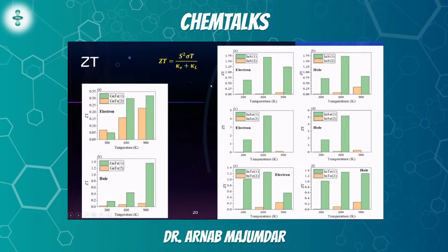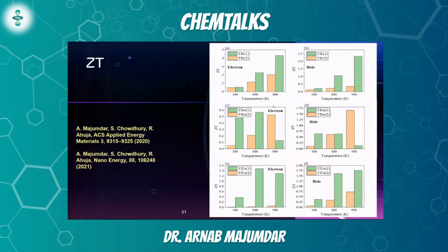But the interesting thing is that for all these systems, we can see that the ZT value for our systems, which is represented in green, is consistently higher and significantly higher compared to that of the AX2 structures already reported in literature. This is basically the same for the thallium series. You can see that again, values reach above 4, 2, 1.5, very, very high values once again. And the same trend is noticed. That is, for the AX1 structure, which is our structure, it's always comparatively much higher compared to the AX2 structure.